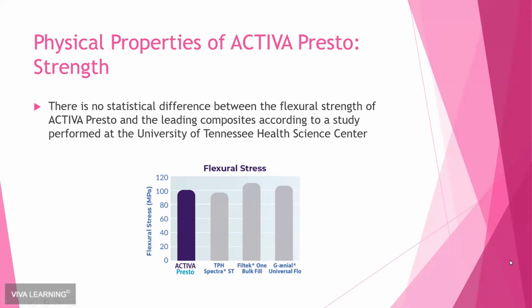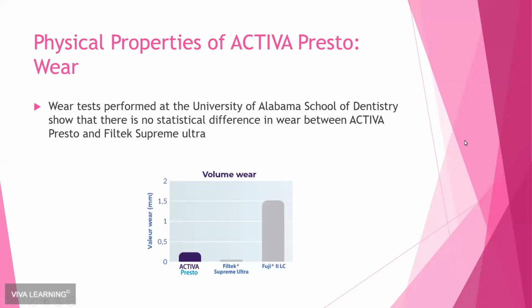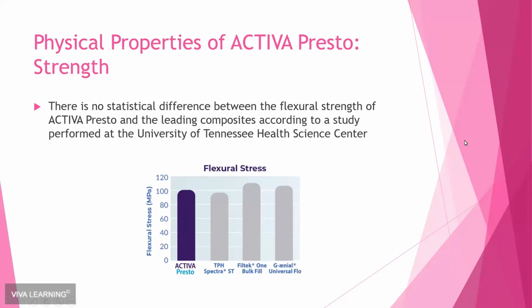When we're looking at the strength of this product, there was a study done at the University of Tennessee Health Science Center that compared the Activa to TPH Spectra ST and the Filtek, and they found that there was no statistical difference between the flexural strength of the Activa Presto and these leading composite brands. So even though this is a flowable composite compared to a packable composite, the strength is still comparable.